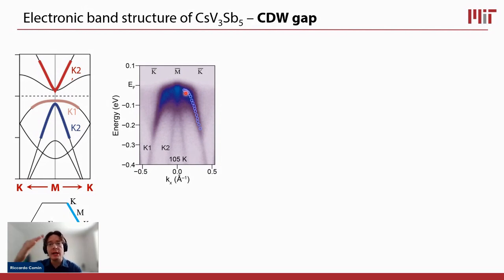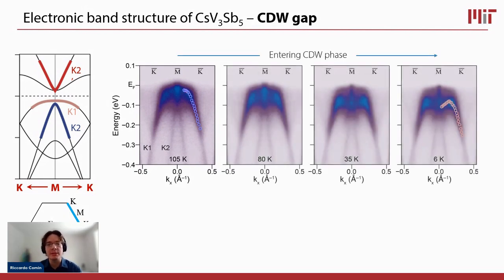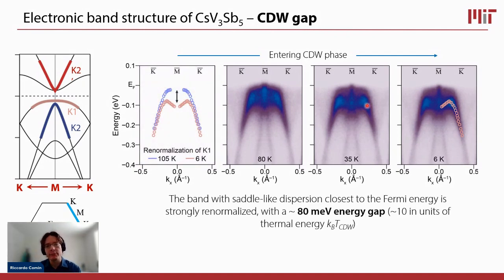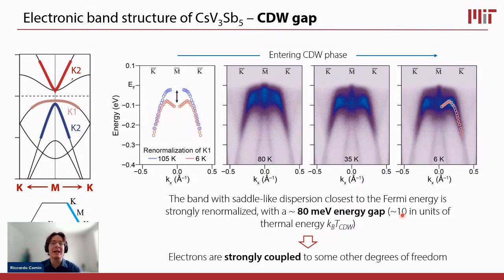As we lower the temperature and enter the broken symmetry phase, these bands get pushed down, renormalized in energy by a massive amount, of order 80 milli-electron volts. So there's an energy gap that opens up at the Van Hove singularity as large as 80 milli-electron volts, which in units of kB T_CDW, the thermal energy for the charge density wave transition, is of order 10. And 10 is a big number. That means that the electrons are strongly coupled to some other degree of freedom.